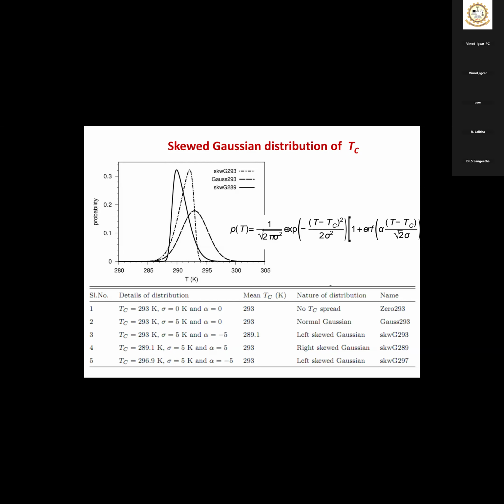See, for example, say you are making a magnetic material and its transition temperature is 300. A symmetric Gaussian means, suppose the spread is 50, the transition temperature can go from 250 to 350. But in actual material, it is not the case. Suppose you are making the material with a transition temperature of 300, most of the time the phase purity is 80% or 90%, so most of the material's transition temperature distribution will be biased close to 300. Only a small fraction will have variation around the 300. So I can say the spread will be around 250 to 310.